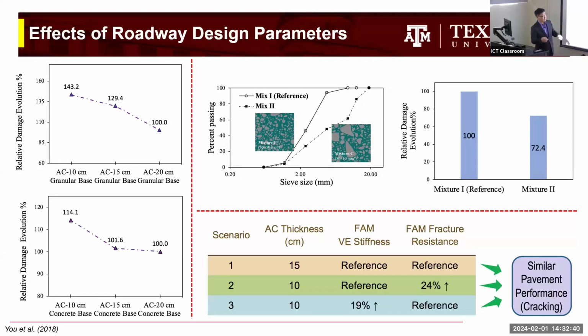So here are some results we got by changing the base layer type, like granular base versus concrete base. The trend of the damage evolution is quite different depending on the stiffness of the underlying layer. This is a case with different microstructure, coarse aggregate gradation versus fine gradation, with different levels of damage. And this table tells you how we can even optimize or select the mixture design and structural design for target performance by playing with your design variables. You can play with the thickness of a layer, the property of a layer, or both.